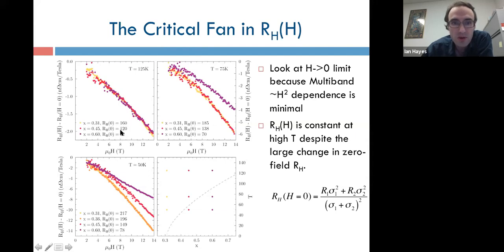Now I just want to bracket this for a second and point out that this is what you expect to happen just from multiband physics. The conductivities on all these sheets are getting better as you go toward the overdoped side, and so you expect this term to get smaller and smaller, as this in fact does. But if you just compare the field-dependent part and just look at this decrease of RH with field, that part is exactly the same at high temperature. It's fairly small, but it's resolvable, and the curves lie right on top of each other.